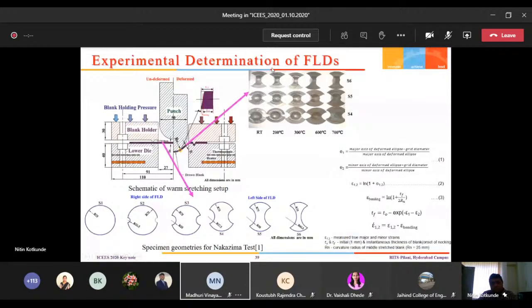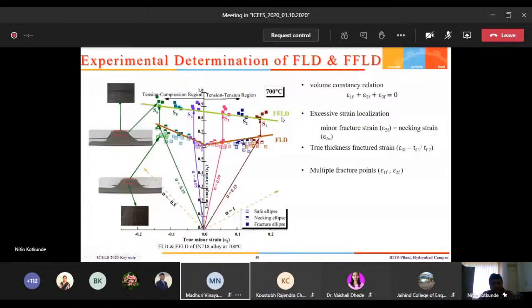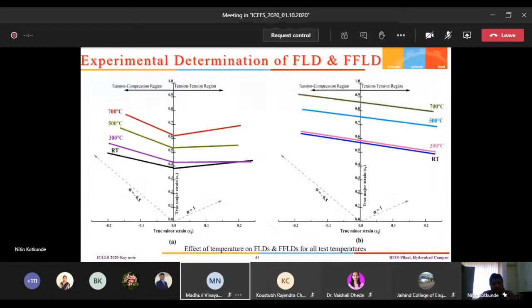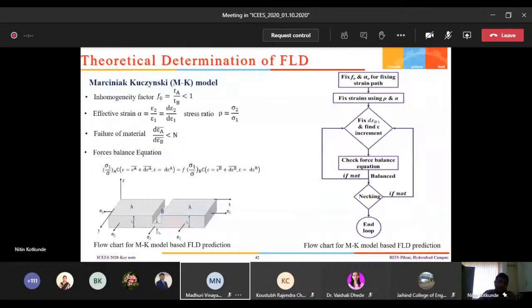These are the standard specimens which we deform at the different temperature regions, and these are the FFLD, fracture based FLDs. These are the FLDs, and that can be corrected. The bending strain effect can be corrected by using bending correction stress, which are shown here. So this is the experimental FLDs which we have drawn, and that needs to be validated using the numerical